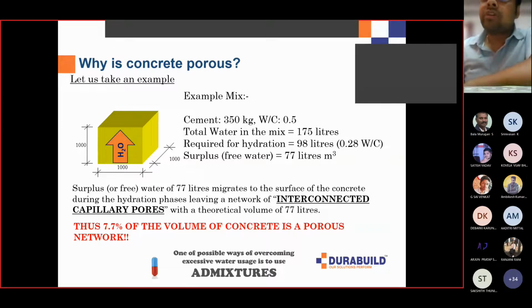And what is the purpose of adding this free water? That is to give workability, to give a little flow to the concrete, otherwise the concrete does not flow and then you cannot place it inside the slab. But the negative side of these 77 liters is that it migrates to the surface of the concrete and leaves a network of interconnected capillary pores, which will have a volume of around 77 liters. As you understand, as per this particular formula, almost 7 to 8% of the volume of concrete is a porous network. Now you will be concerned. If you have a porous network, then there is likely movement of water, and waterproofing issues may come up later on. There will be many more issues. Cracks will happen, shrinkage, this, that. So our idea, one of the possible ways of overcoming the excessive water usage, is to use admixtures. So what you can do is reduce this water.